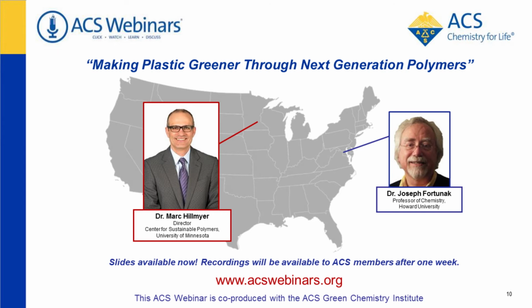All right, now a question that's a little more technical. What's your perspective on optimum glass transition points for these renewable plastics? They have to perform in Arizona and Minnesota. The idea here is that in the case of the block polymers, which remember are hard block, soft block, hard block, you really would like the hard block glass transition temperature to be over 100 degrees Celsius. That's the general rule of thumb. But there are applications where you would want higher than 100 degrees Celsius, for example, in adhesives that have to perform in high temperature environments, where you really would like them maybe higher, around 150 degrees Celsius.